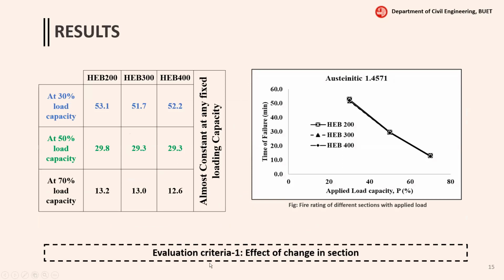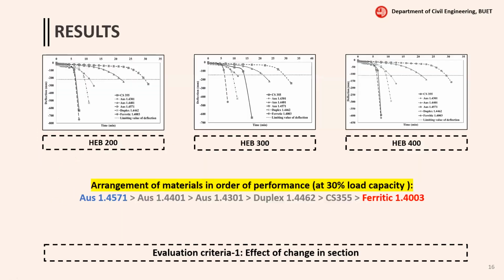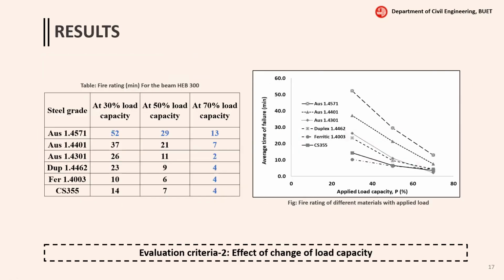Okay, moving on to our first evaluation criteria. For austenitic 1.4571, analyzing the effect of change of beam section, it can be seen that at a given load capacity, the change in beam section had almost no effect on fire rating when the loading was constant. The pattern was repeated in all the sections and for all the materials, as the failure patterns were almost the same.